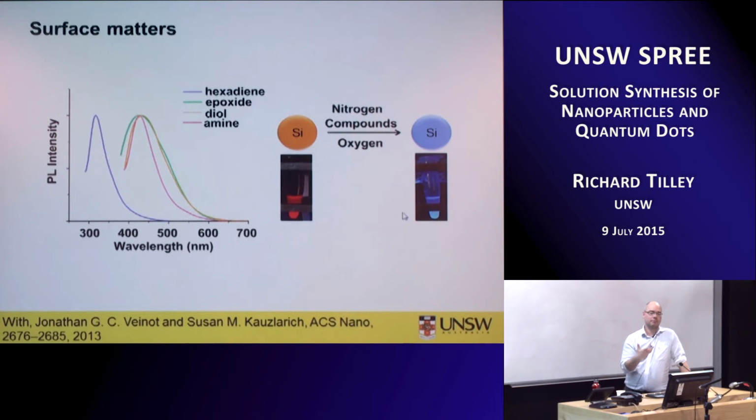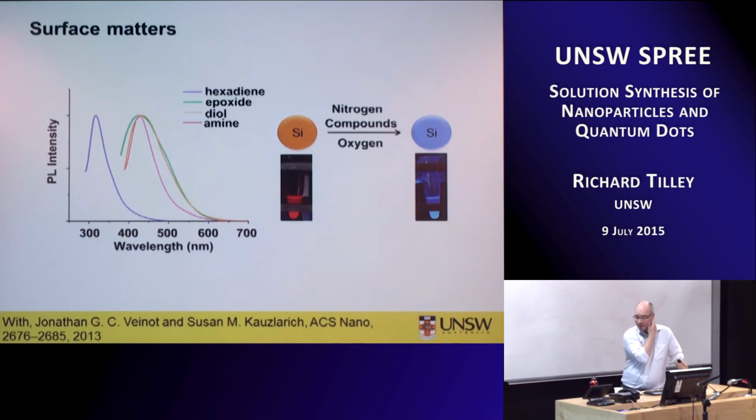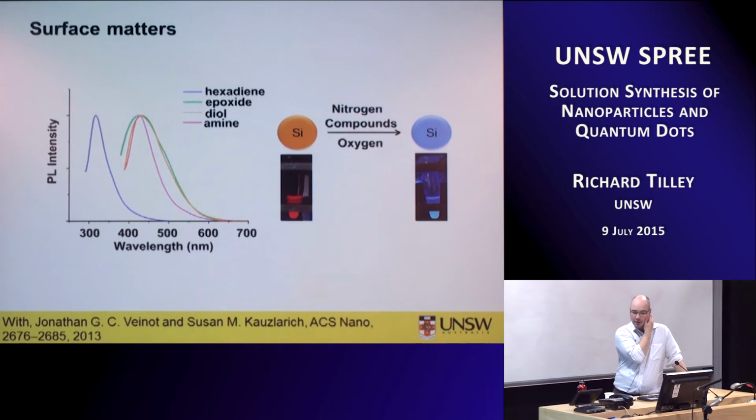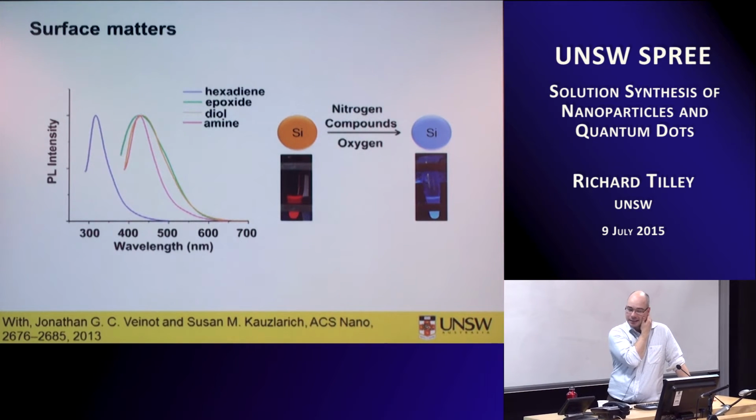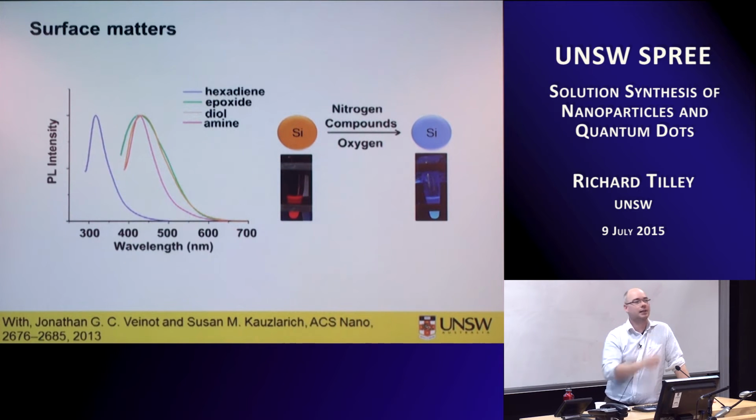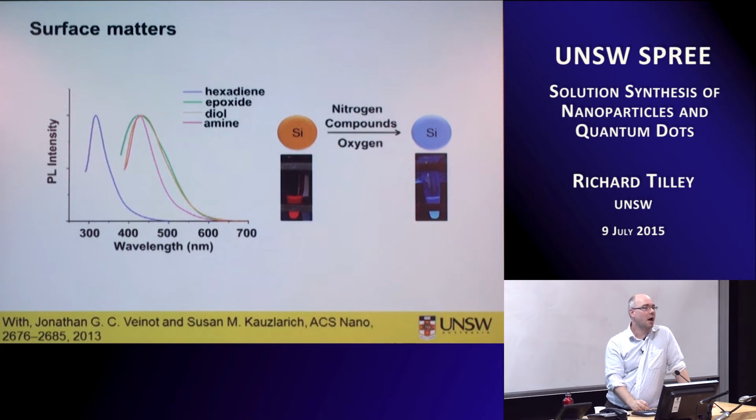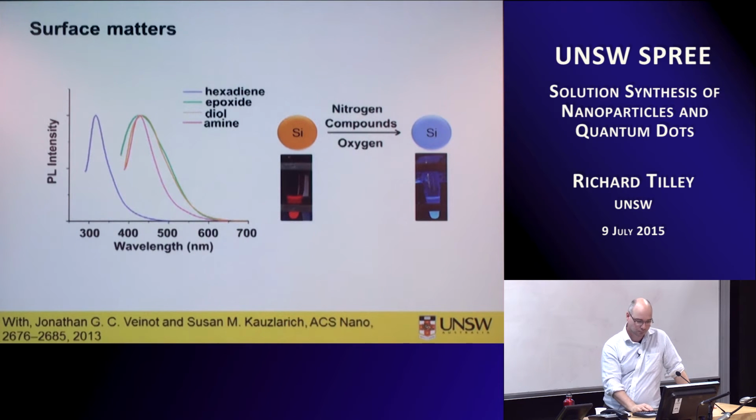So his hypothesis was that if you're getting out a blue color, it's probably coming from some silicon-nitrogen entity in the dot or on the surface of the dot, and that was the transition he saw. So we had a good look at our dots and compared them to his dots, and that seems to be about the best bet in terms of where the emission comes from. So probably it's coming from a silicon-nitrogen bond or entity on the surface of the dots.